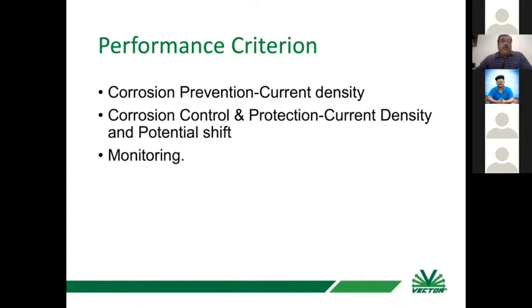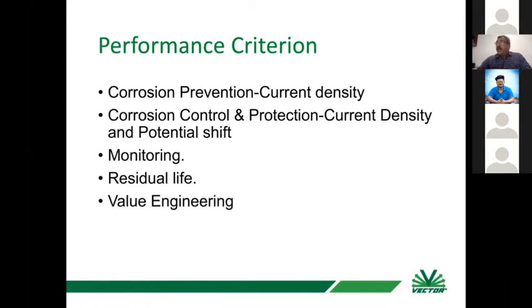We should be able to monitor the system so that we can know that yes, whatever I had spent on preventing the corrosion of rebar, it is performing. And residual life: even after the consumption of zinc or the metal in the anode, by doing a sacrificial anode system or cathodic protection, you have made the pH good. You have made the environment around the steel good for corrosion protection. So you can have a residual life after the consumption of the anode also. It will last a long time, a few years more, before reinitiation of corrosion. And value engineering, like how much money is likely to be spent.